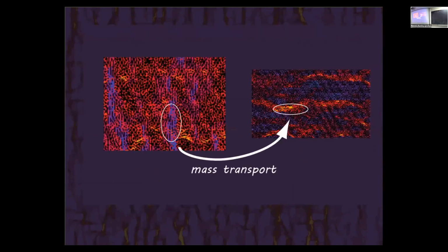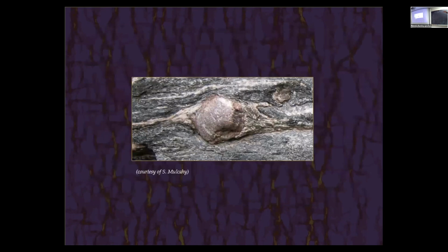And here's the notion that a quartz grain stuck in one of these very high compressive stress areas may dissolve or diffuse away from there, and then park itself in an area where there's more tensile stress. So it'll be just like the garnet, right? Basically the whole material is behaving the way these little stress spheres on the garnet behave.